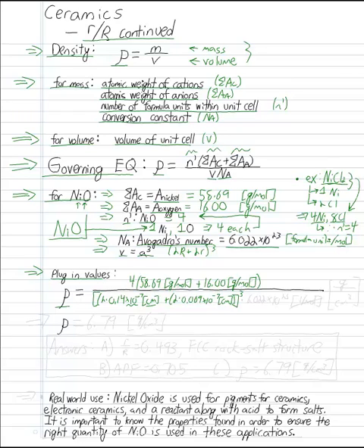This expression is cubed, since it's the volume, and we'll multiply it by the conversion constant, 6.022 times 10 to the 23rd. That's going to be 1 over moles. We have 1 over moles in the numerator and 1 over moles in the denominator, so that cancels out. This leaves us with grams per centimeter cubed for our units. Plugging that in, we can see our density is equal to 6.79 grams per centimeter cubed.